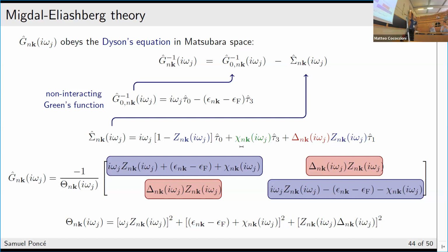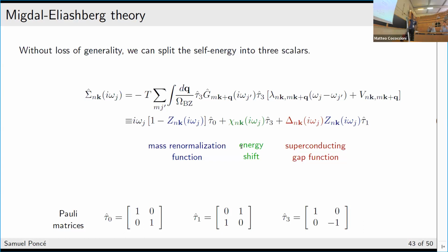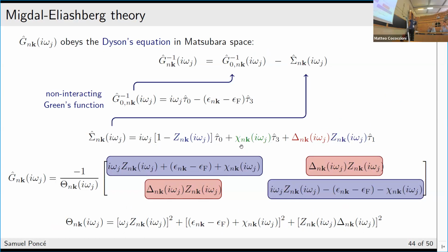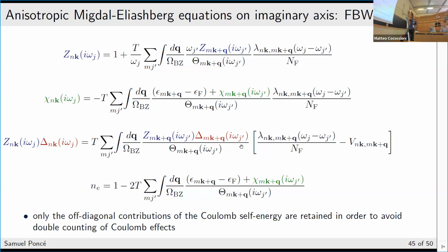and then we obtain this equation, in which in the diagonal you have this z term, this chi term, and then this gap term, okay? And you also have this, which is defined here. And what you do is that you just take this formula and you map it with this one, okay? And by mapping the components, you then end up with these three equations. So those are the ones that map these three parameters that we have introduced to the Green's function and the self energy that we have in the theory.